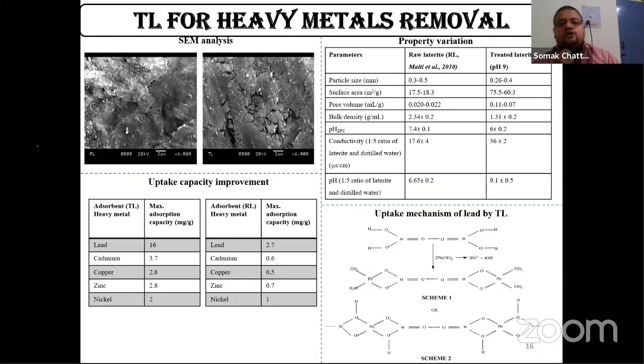Since our surface becomes negative, most of the heavy metals, for example lead, cadmium, zinc, nickel, chromium, which are positively charged, will be attracted by the adsorbent. This corroborates the reason for this. For example, the maximum adsorption capacity for raw laterite was 2.7, whereas after this treatment it increased to around 16. For cadmium, copper, zinc, and nickel, though it increased, we were not able to find such a comprehensive increase in removal. However, for lead, there was more than 5 times increment in the adsorption capacity. Thereby we looked into X-ray diffraction and other sorts of characterization as well.